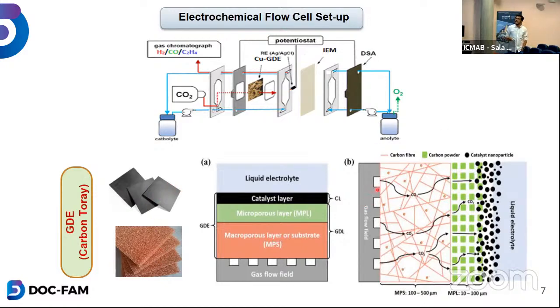The main principle is that gas flows from this side, and we have a carbon microporous layer and the catalyst nanoparticles, copper, the one that I'm working on. And here we have the liquid electrolyte that comes all the way like this. The main idea of a gas diffusion electrode is that it should allow the gas to pass through from one side, but because of its hydrophobic nature, we can avoid electrolyte moving back into the electrode and flooding the gas diffusion electrode. So we can have a very good catalyst layer here, and then we can develop the hydrophobic effect by deploying some PTFE or ionomer-based materials, like Nafion or Fumion, which I'm using now.